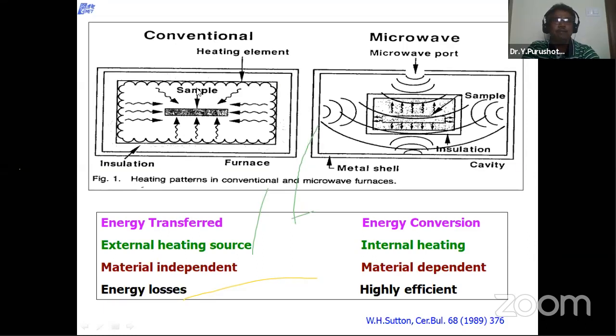Now in conventional heating, which is nothing but resistance heating, the target temperature is first reached by the heating elements, and then the sample is heated by conduction, convection, and radiation, which requires a long duration to reach the target temperature. In conventional sintering, after reaching the set temperature, coming back to room temperature takes another few hours. So from start to end the material is unnecessarily exposed for a longer duration, which can result in grain growth. Unlike conventional heating, in microwave heating the material itself absorbs microwave energy within no time.